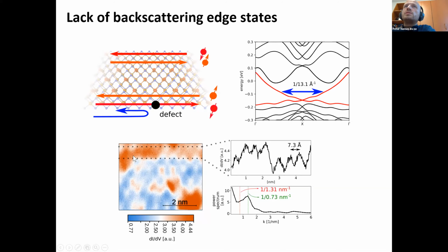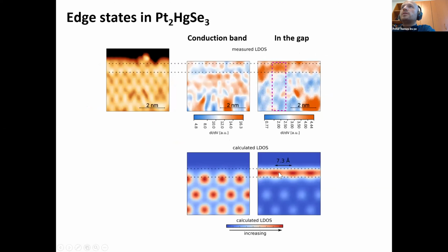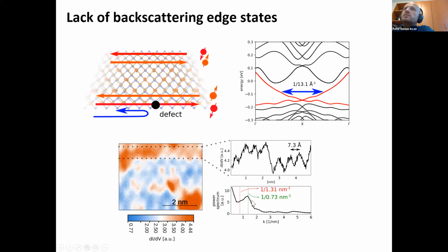So what you can do is you can take the density of states measurement along the edge and do a Fourier transform along the edge and look for what kind of periodicities you have there. So of course, one of the periodicities is the 7.3 angstrom of the unit cell periodicity. This, of course, you expect to have in there. You can also see it on the calculated DFT image. But if we do a Fourier transform along this edge, you can see that at the expected wavelengths of the backscattering, you have no signal.